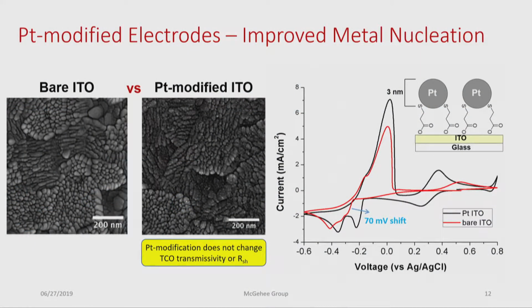So for you electrochemists out there, we ran some cyclic voltammograms on this, and you can see when we introduce the platinum to this TCO surface, the onset potential for metal nucleation shifts about 70 millivolts. And that's exactly what we wanted to show. So what we're showing here is that the overpotential for metal nucleation is now lessened with this platinum modification. So platinum provides a much better surface for metal to nucleate compared to our normal ITO. Now I get it, some of you may be thinking that 70 millivolts, it's really not that much. But it's substantial because it changes the mechanism by which the nucleation is limited.